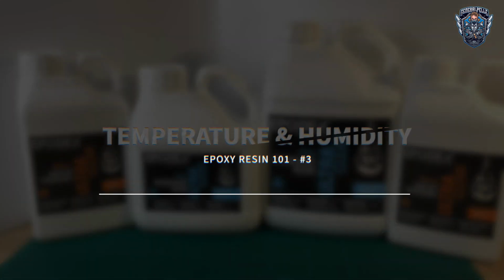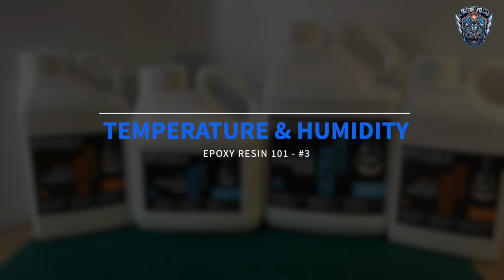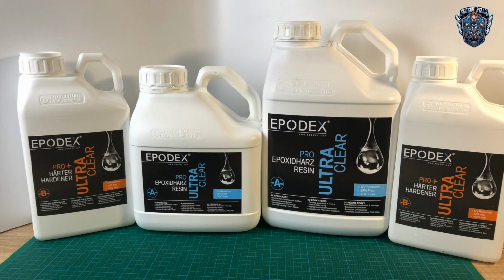Another thing to look out for is the room temperature and humidity. Usually these liquids have their sweet spot at around 20 degrees Celsius, which is around 68 Fahrenheit for all you American followers out there. If it gets under 15 degrees, it will cure too fast, making it vulnerable to scratches. If the temperature is too high, it might not cure and stay liquid, or burn your house. The humidity also should not go above 70%, so make sure it's not too wet in your room.